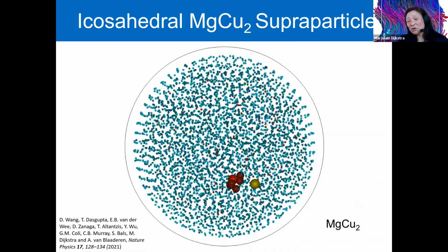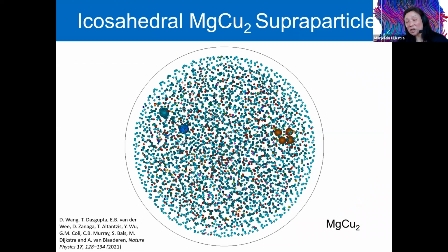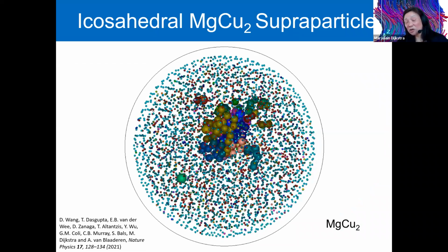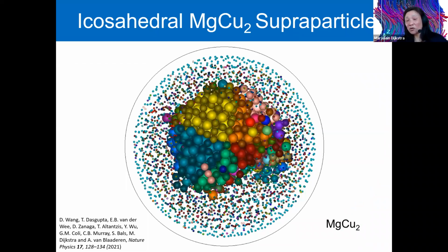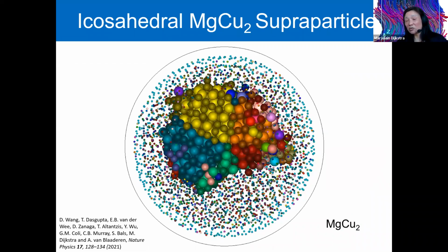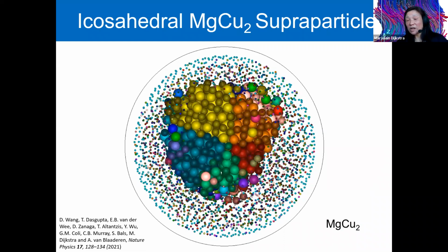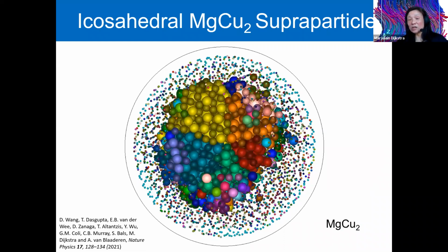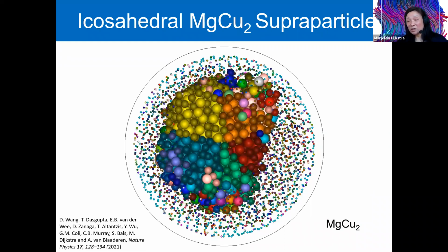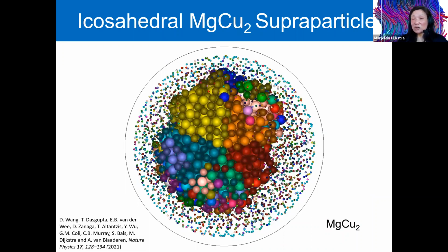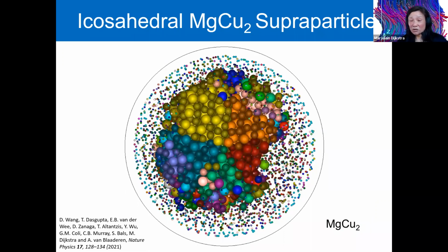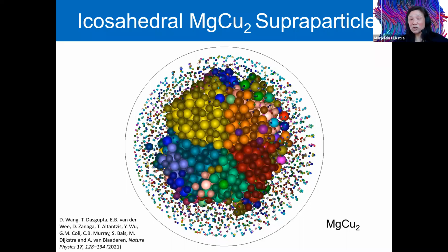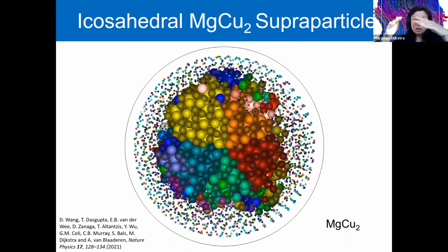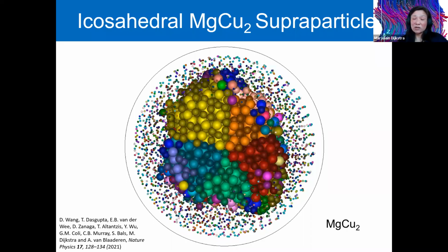In simulation, we could also analyze the crystallization mechanisms. Here we find that the crystallization really starts at the off-center position in the spherical confinement, and then from there on, it tries to grow these 20 tetrahedral domains. So it's a completely different crystallization mechanism than in the case of just pure hard spheres, where it started to grow from the outside to the inside.